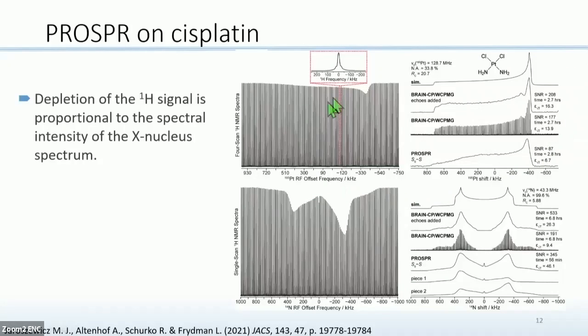So here, our first test case was cisplatin. On the left, we see these Z spectra that I was talking about, and on the right are the processed spectra, and we compared them to optimized broadband acquisitions of BRAIN-CP. First of all, if we go back to what I said earlier, we see that the depletion of the signal on the proton is indeed proportional to the spectral intensity of the X nuclei.